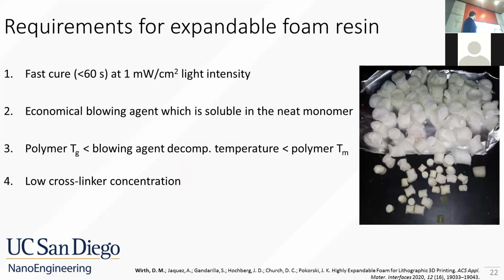To reiterate the requirements for this novel foam: we want something that can cure quickly at low light intensity, because commercial mass SLA systems typically have a little bit lower UV light intensity. We need a blowing agent which is soluble in the neat monomer, and we need this blowing agent to decompose between the glass transition temperature and the melting point of the polymerized resin.